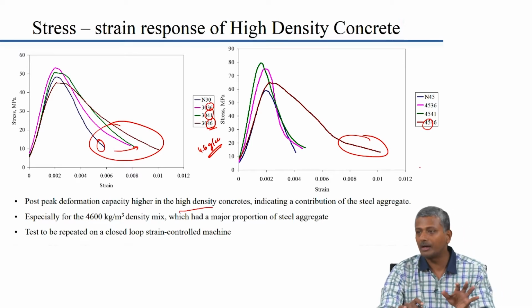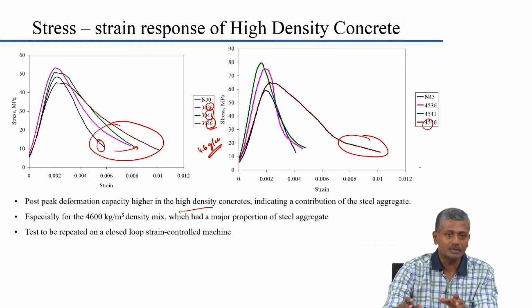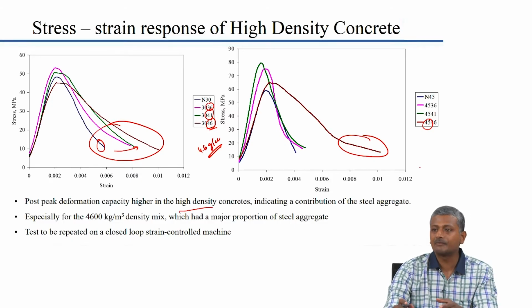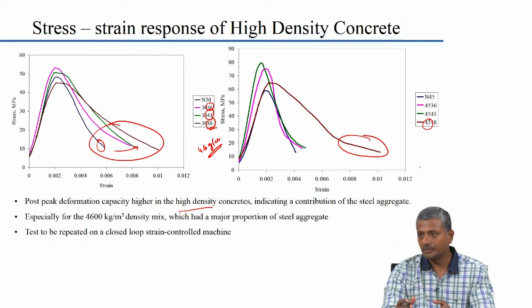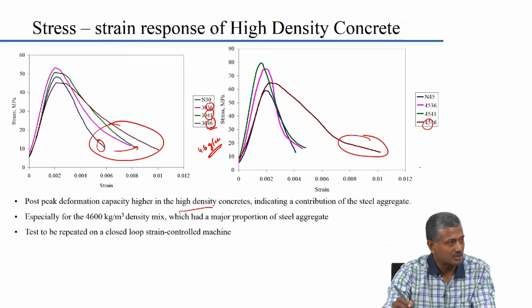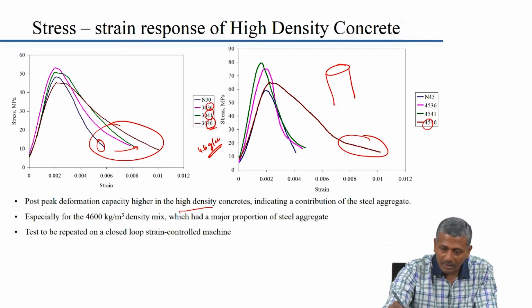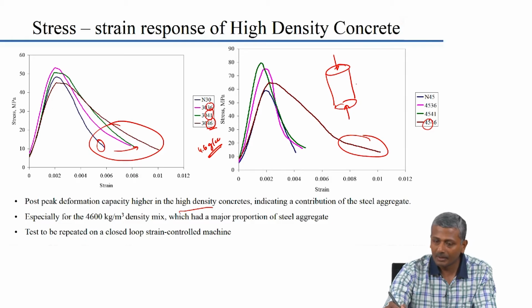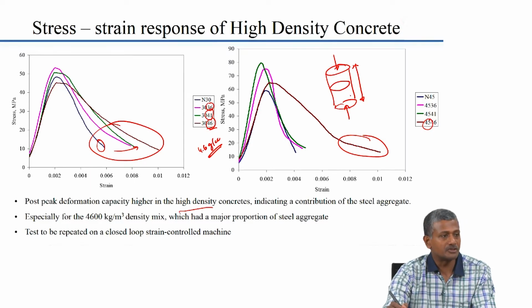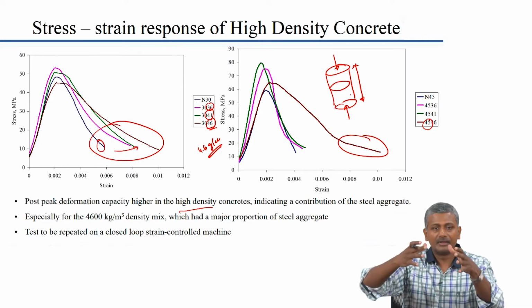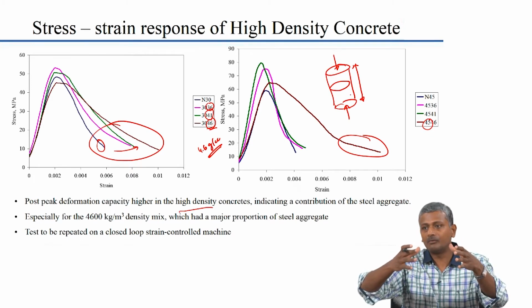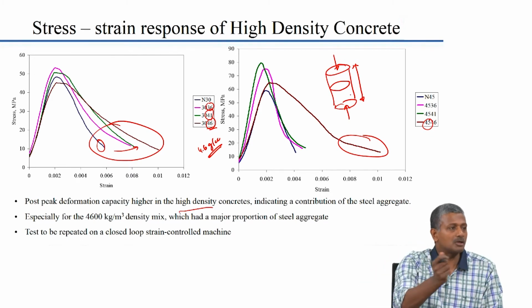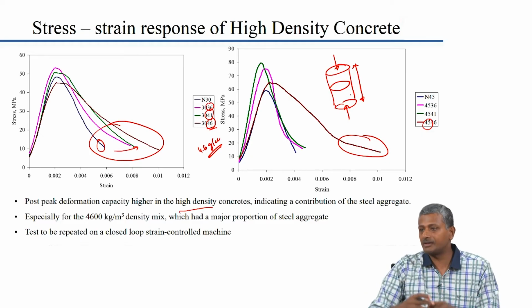So, again, I do not have full faith in these numbers, of course, because these were done with a setup which was not truly deflection controlled. In the case of a compressive deflection control, what you need to control is the rate of circumferential expansion. If a cylinder is getting loaded in uniaxial compression, it is not this deformation that we need to control. What we need to control is the circumferential expansion, because when the cylinder is getting compressed, it is trying to bulge outwards, and that outward bulging is what we need to control if we want to get a slow and steady failure rate.